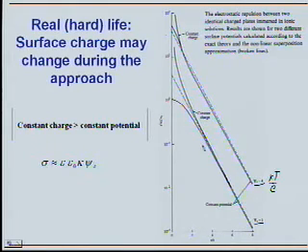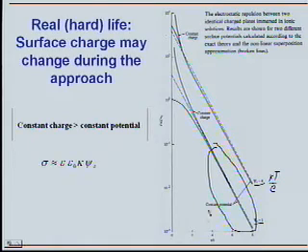What you're going to see is that there is not much deviation between the formulas that we derived and the actual force, for small potential, down to a distance of about 3 times 1 over kappa. So this is kappa times h: 1 over kappa, 2 over kappa, 3 over kappa, and so on. This is the dimensionless distance in terms of kappa.